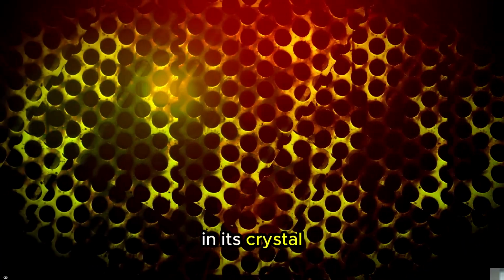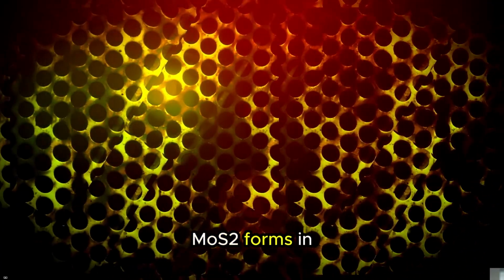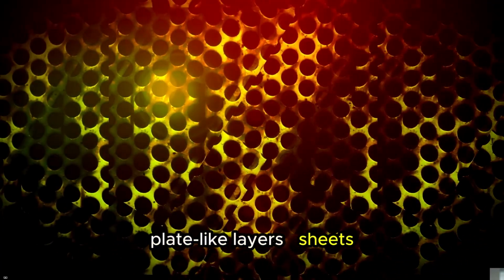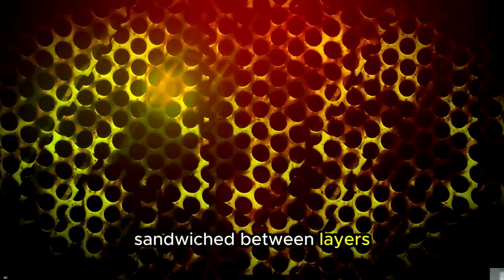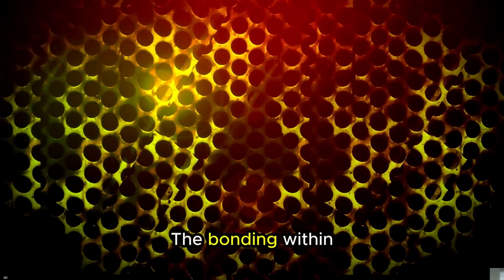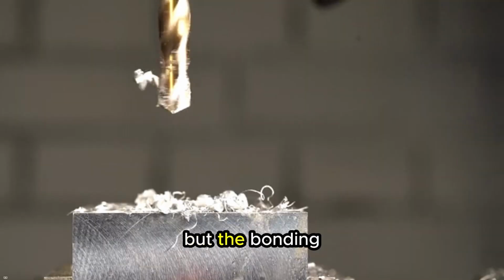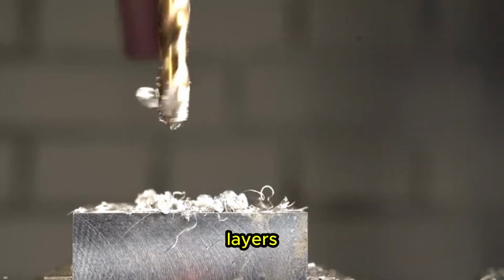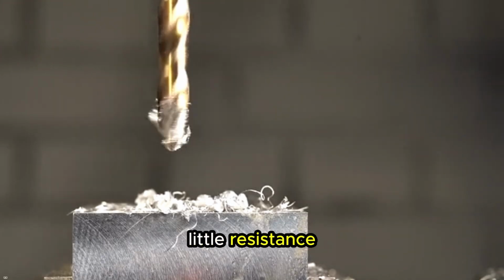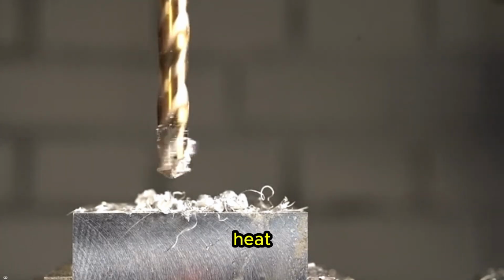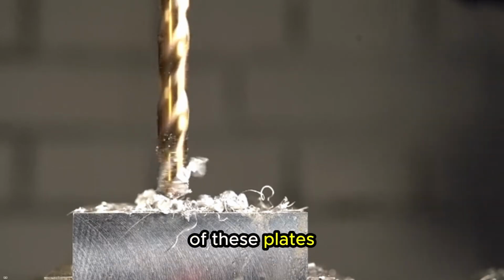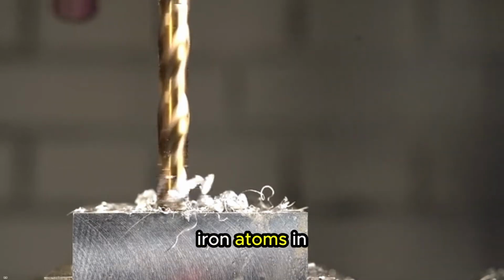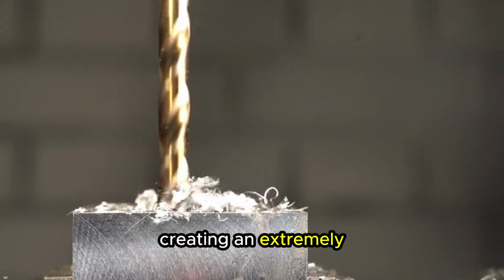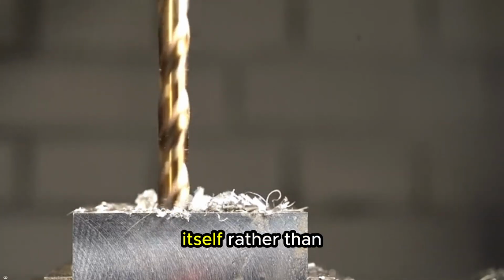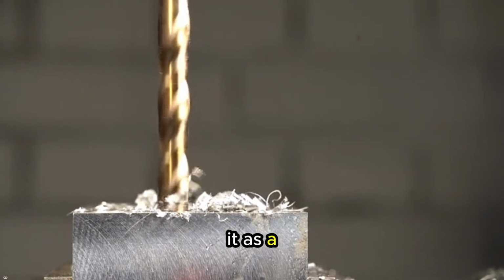The reason lies in its crystal structure. MoS2 forms in hexagonal, plate-like layers, sheets of molybdenum atoms sandwiched between layers of sulfur atoms. The bonding within each sheet is strong, but the bonding between sheets is weak, which lets the layers slide past each other with very little resistance. Under pressure and heat, the sulfur atoms at the surface of these plates can also form a chemical bond with iron atoms in steel, creating an extremely thin film that adheres to the metal itself rather than simply sitting on top of it as a liquid does.